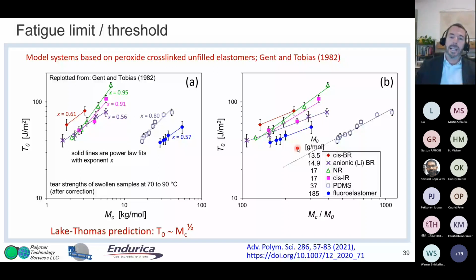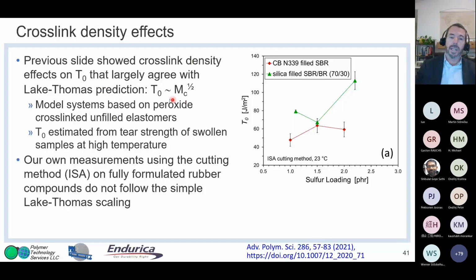When we dug ourselves into cross-link density effects to see if this prediction held, we generally found we did not agree with that prediction. But we didn't do a lot of testing. This was just a couple of systems: carbon black filled SBR, and something that looks like a passenger tire tread, a blend of SBR and BR rubber with silica and silane. When we plotted fatigue threshold from the cutting method versus the loading of sulfur in the formulation, and adjusted accelerator to keep the type of crosslinks similar, we didn't see the expected trend, which would have been a downward sloping relationship. So there's still some work to be done in this particular area.